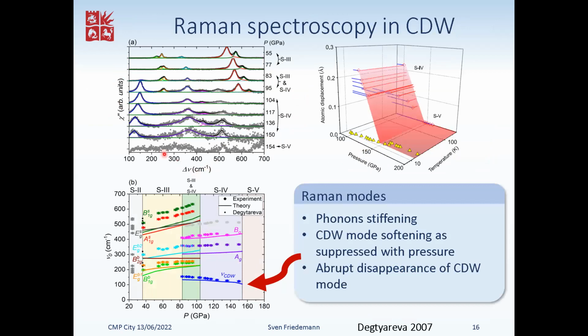So these are Raman measurements. Here in the energy window, or wave number window, from 100 to 700 wave numbers, you can see several peaks, most of which are phonons. Down here are the peak positions. You can see that many of them stiffen as a function of pressure, which is exactly what you expect, the lattice becoming more stiff. This is also true in this sulfur 4 phase, which hosts the charge density wave, except for this lowest lying mode, which is softening as the pressure increases.